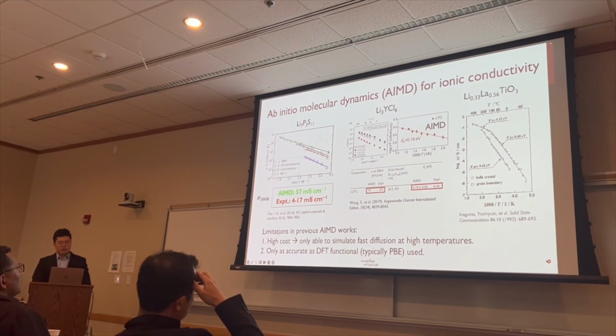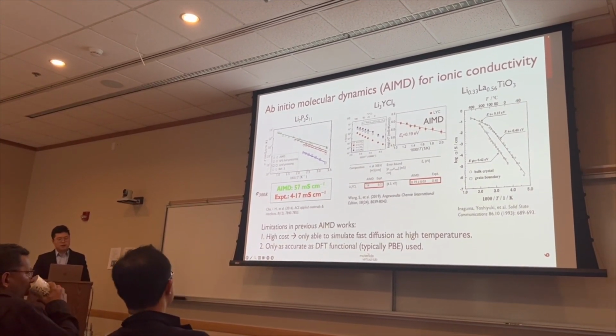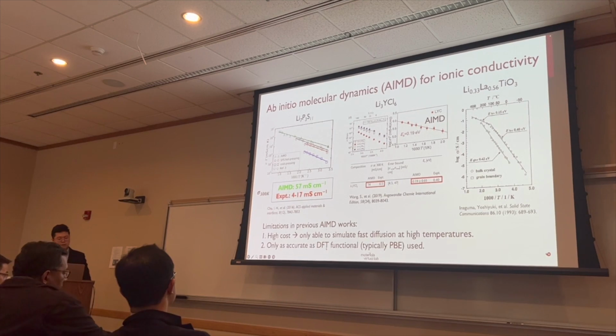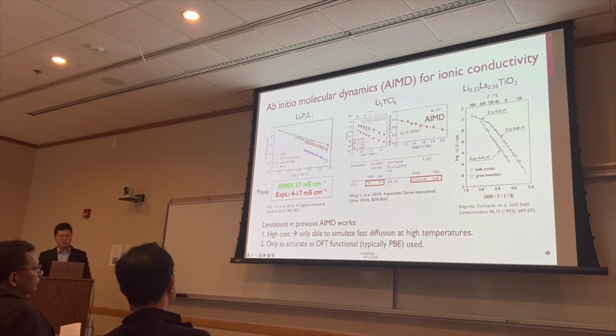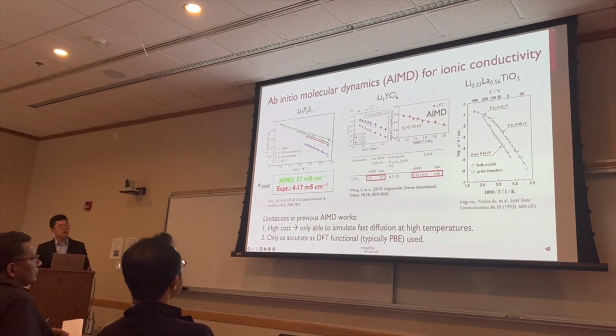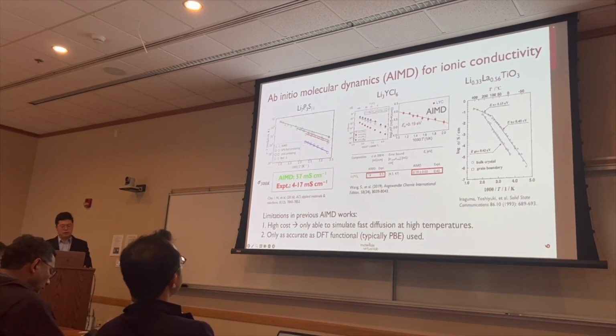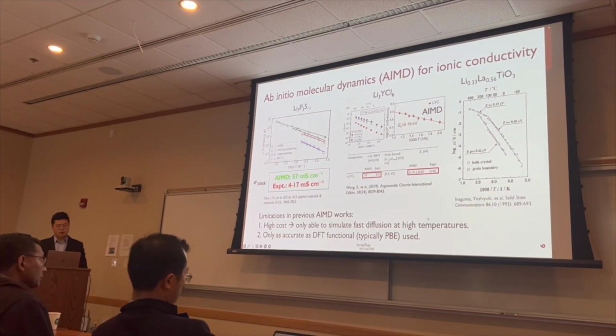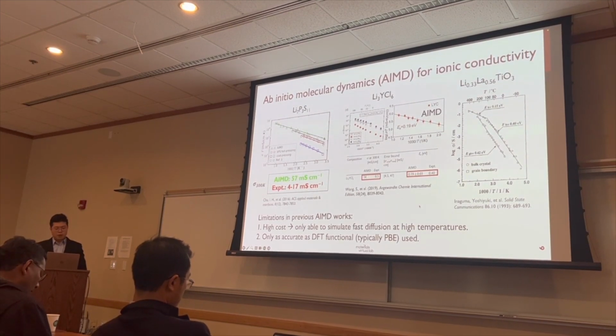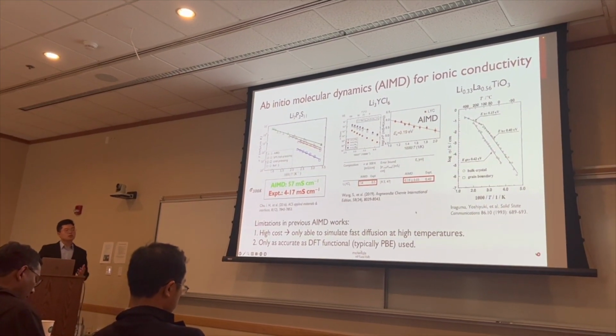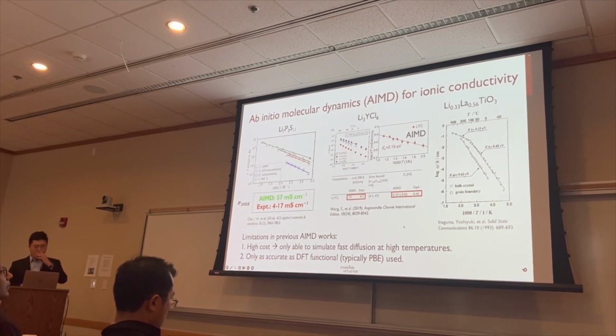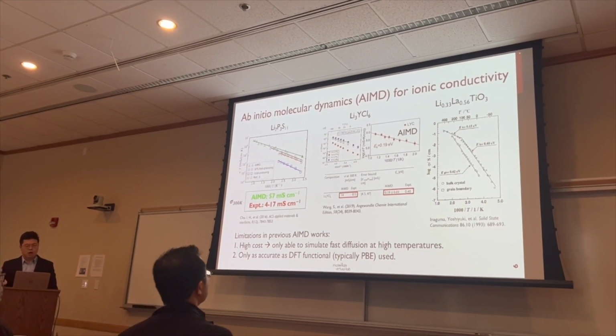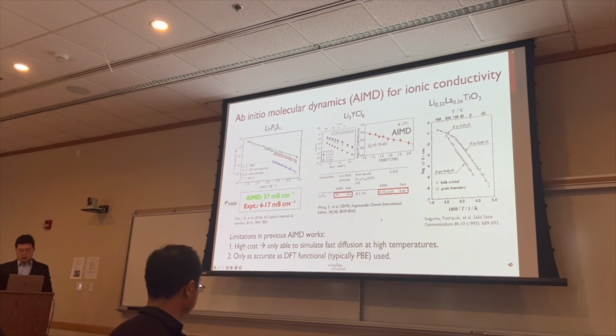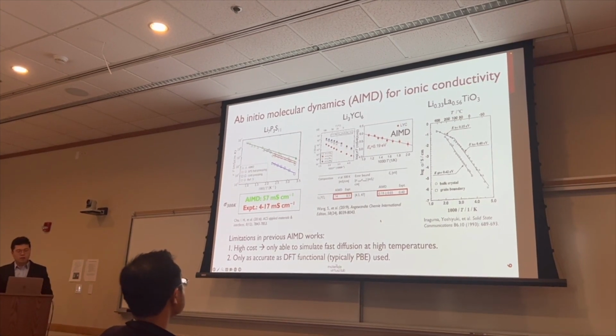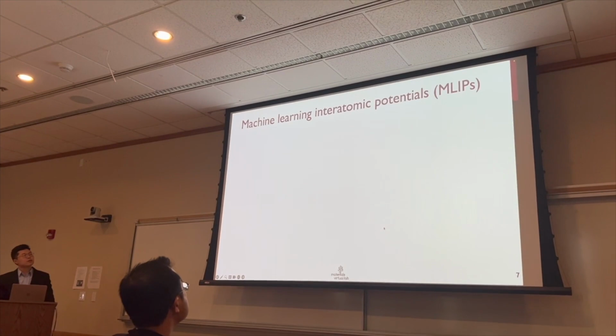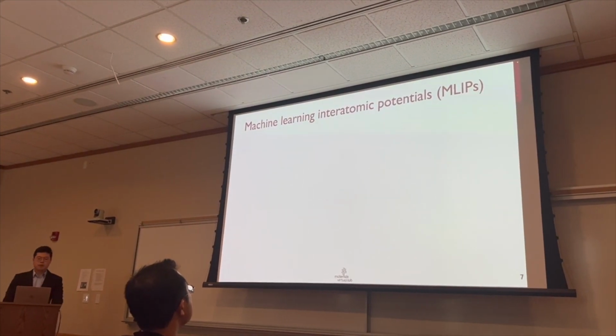And there's another limitation in previous AIMD work, which is that they're only as accurate as the DFT functional used in their simulation, which is the typical PBE functional that is known to have the error of overestimation for lattice parameters. And this leads to some error. So I want to emphasize here, those two limitations of AIMD can all be traced back to the high computational cost of ab initio simulations. And it's probably possible for us to solve those challenges with machine learning interatomic potentials.